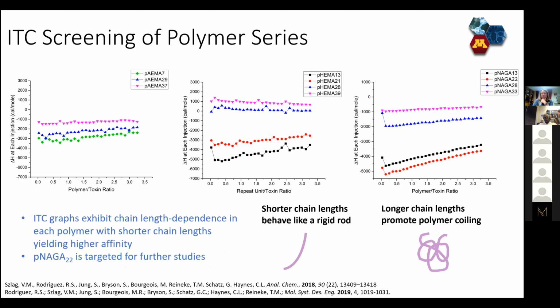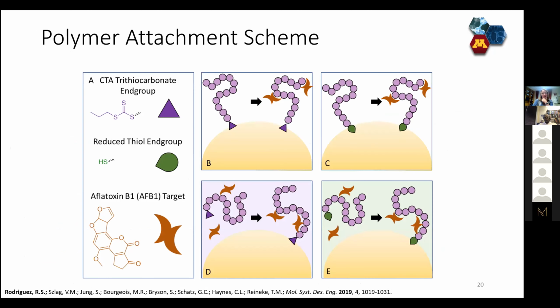So we were essentially using thermodynamics to figure out when there was a really strong interaction, and then we wanted to translate that onto our SERS substrate. So this is a little complicated, but it's showing you kind of how we were going to allow our polymer to interact with our nanostructured surface and how we were going to allow it to interact with aflatoxin. We wanted to figure out what was the way to get the most sensitive system. So in this picture, the little strings of purple circles are our polymer. So think of that as our 22 repeat NAGA polymer. When it has a little purple triangle on the end, that means it has a trithiocarbonate end group.